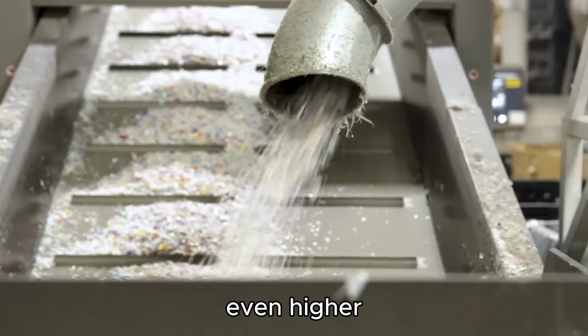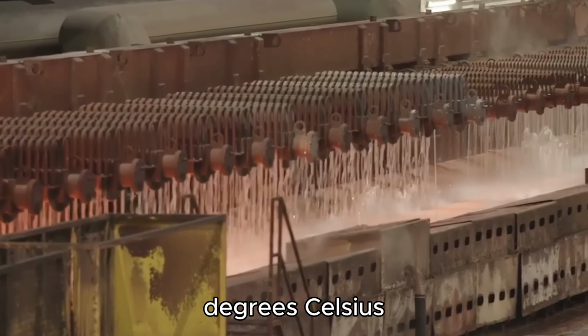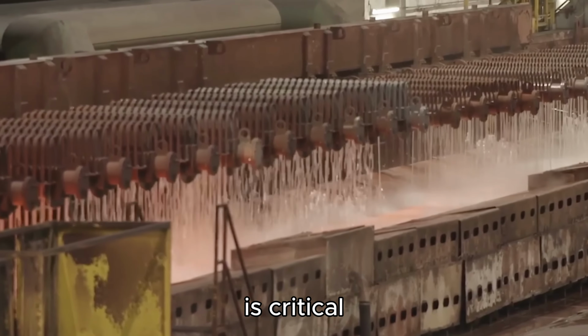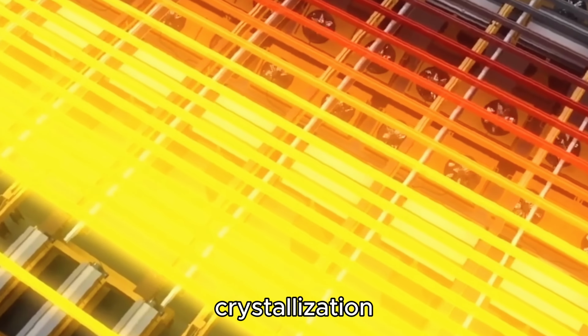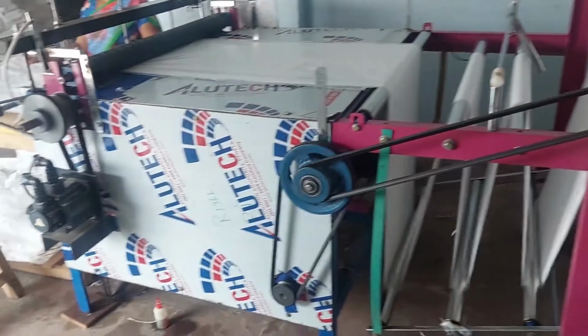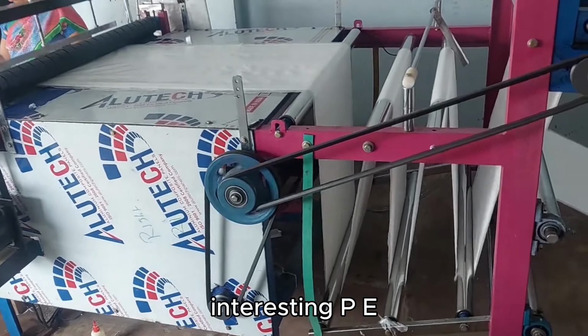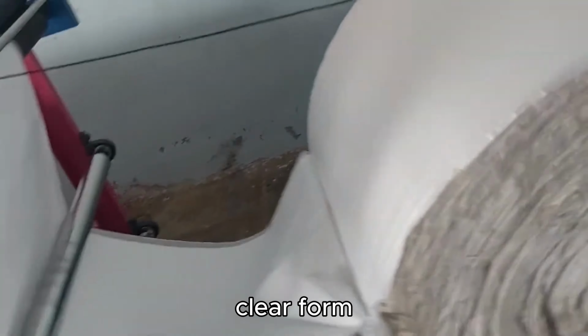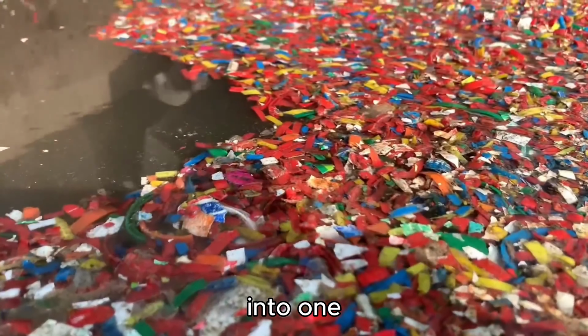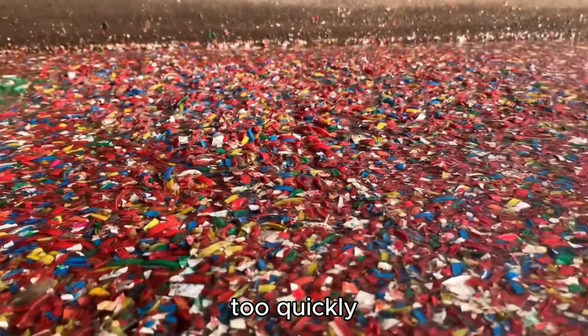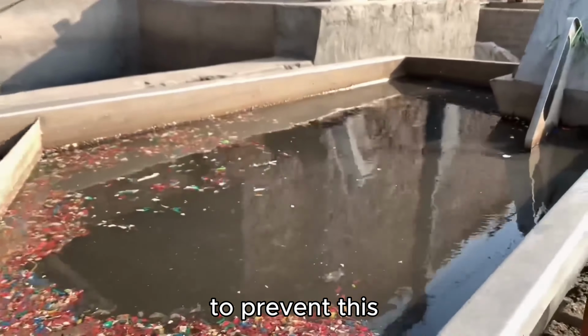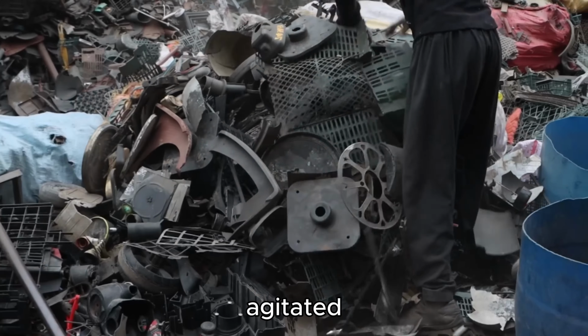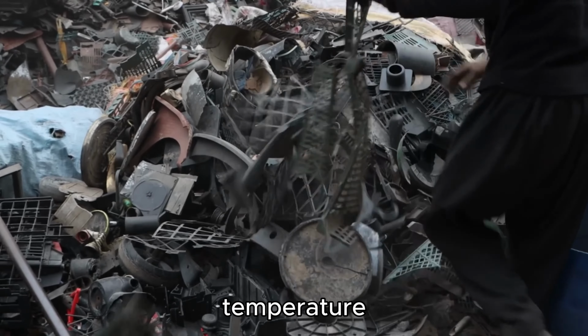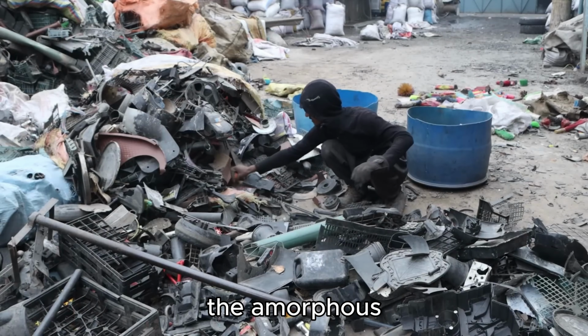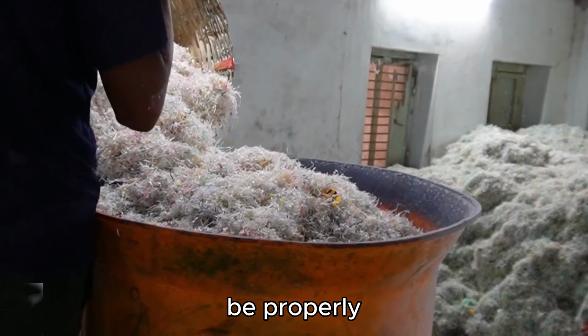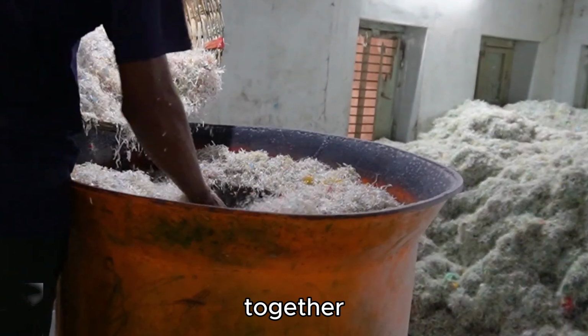PET requires even higher temperatures, around 160 degrees Celsius, but the timing is critical because PET goes through a crystallization process during heating. Here's where it gets really interesting. PET resin often comes in an amorphous clear form that will actually agglomerate into one large mass if heated too quickly. To prevent this, the material must be constantly agitated while being heated through its glass transition temperature. This converts the amorphous PET into a crystallized state that can then be properly dried without clumping together.